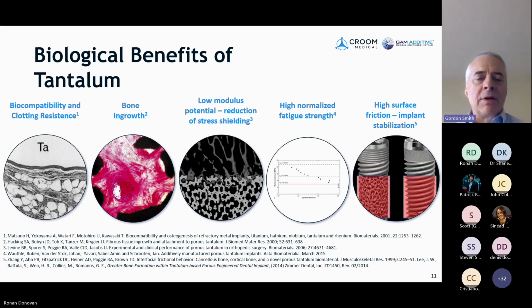So in addition to the ductility that I mentioned on the previous slide, tantalum's modulus is a good fit for preventing stress shielding issues in bones. Again, if the mechanical properties of a medical device material do not match closely to that of bone, then the bone is shielded from the stress leading to bone loss. Tantalum has a high normalized fatigue strength. Tantalum should not catastrophically fail if it were to be deformed over a significant number of cycles, which is a nice benefit.